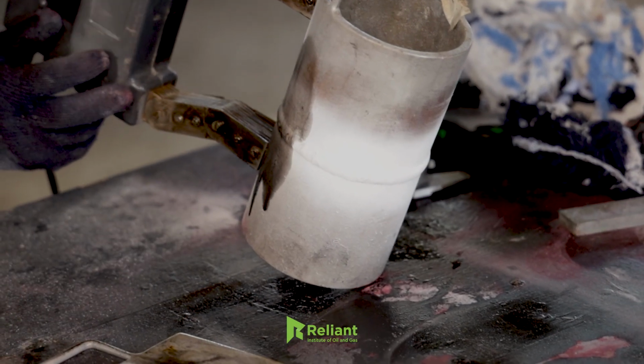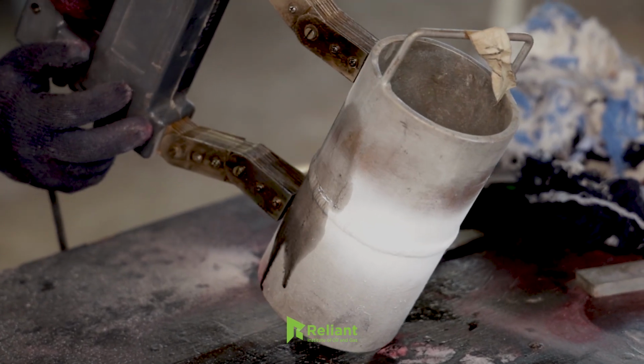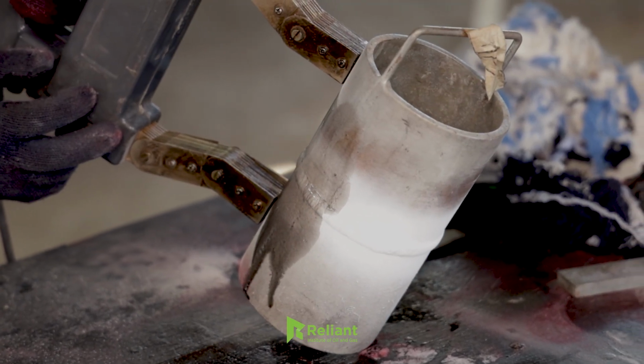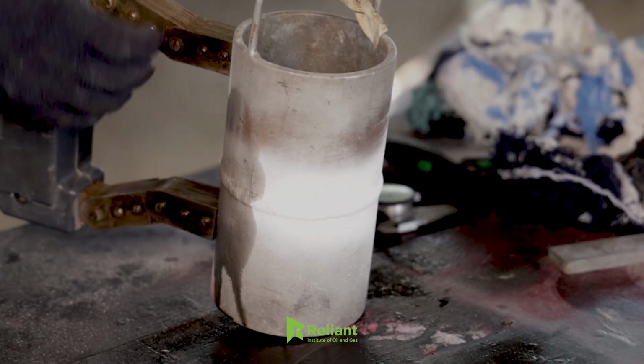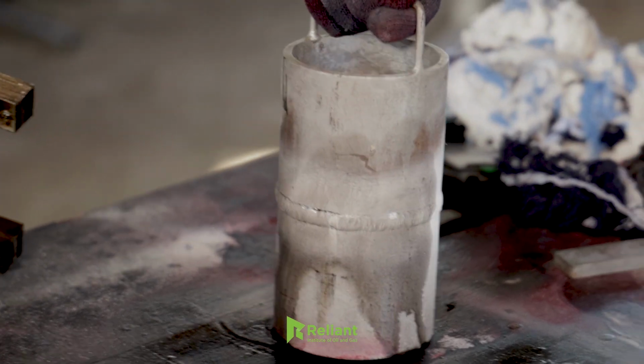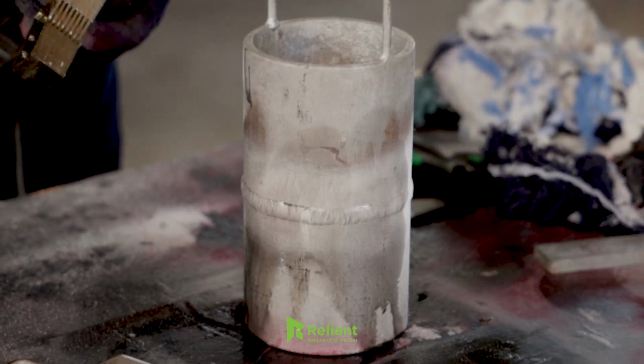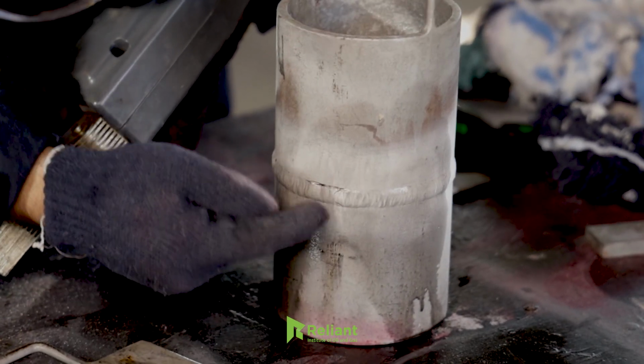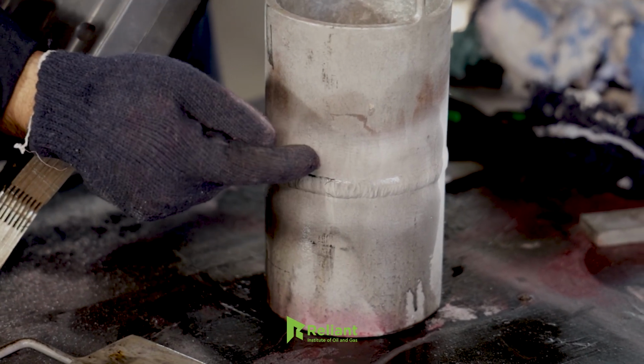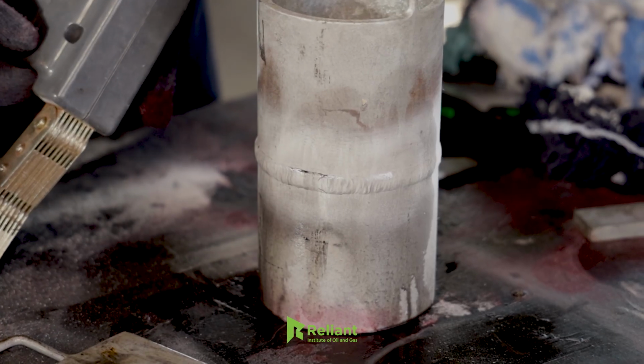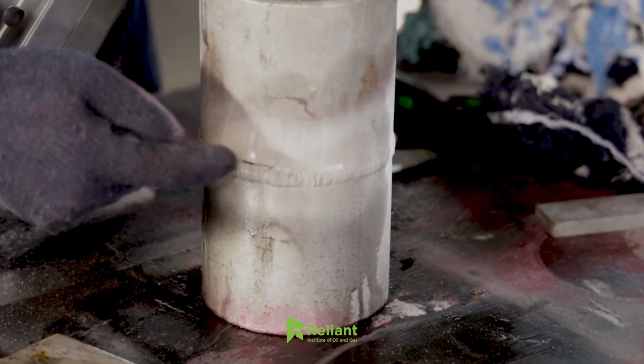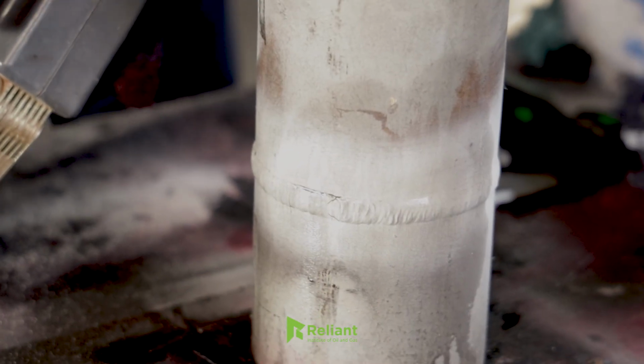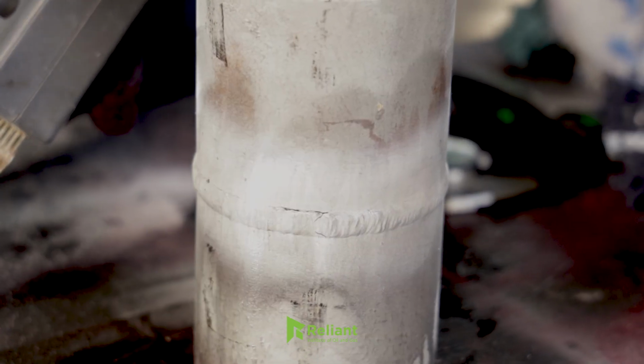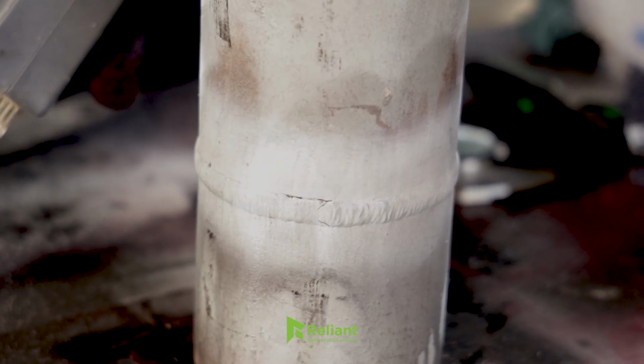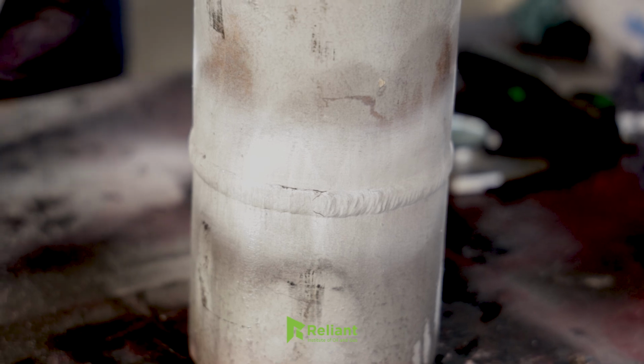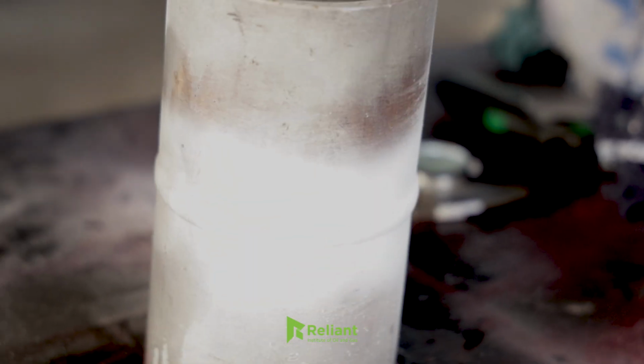Okay. So beautifully an indication has developed here. So I can show that here a toe crack has radiated into the weld material. So here there are 2 cracks available, from the bottom plate and the top plate. Now I am continuing.